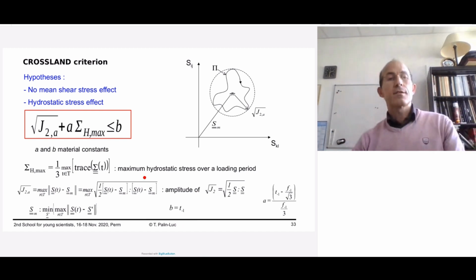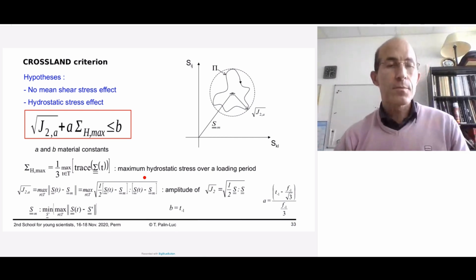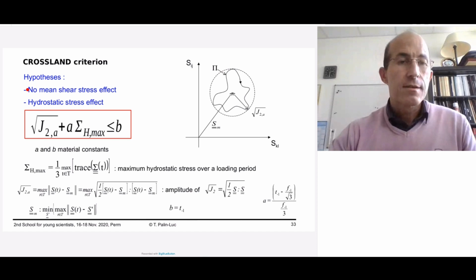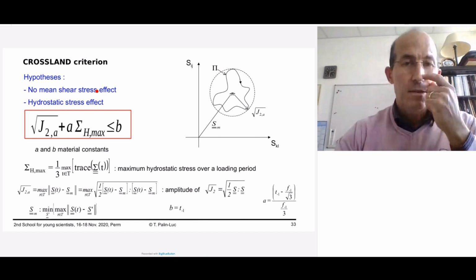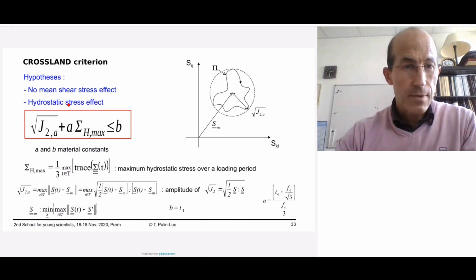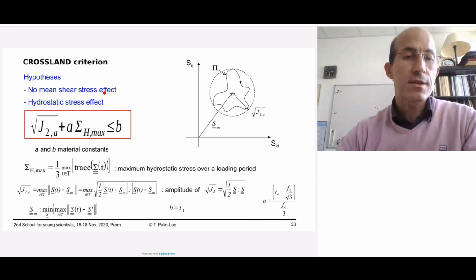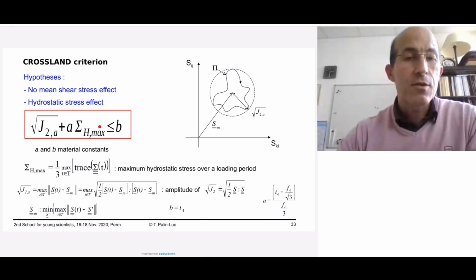So first, the Crossland criterion is based on two important hypotheses. I told you about the fact that the mean shear stress has no effect on the fatigue resistance in high cycle fatigue. So Crossland uses this assumption and also uses the fact that if there is a micro defect, the opening stress of these micro defects in all directions, this is hydrostatic stress, is very deleterious on the crack initiation phenomenon. So he proposed the simplest combination of a shear amplitude, because there is no effect of the mean shear stress, and a linear combination with the macroscopic hydrostatic stress and its maximum value.